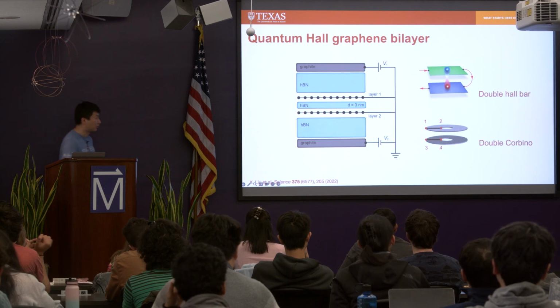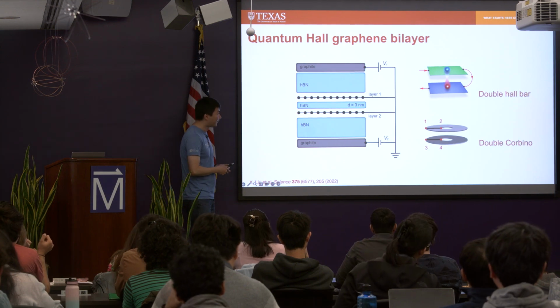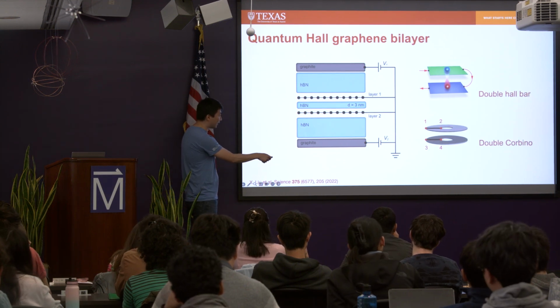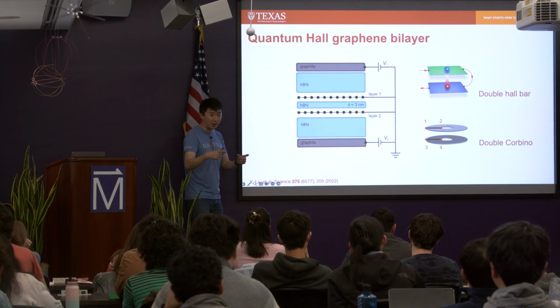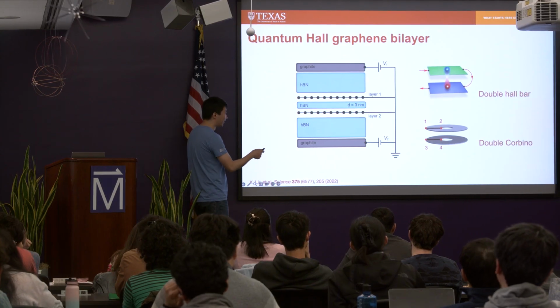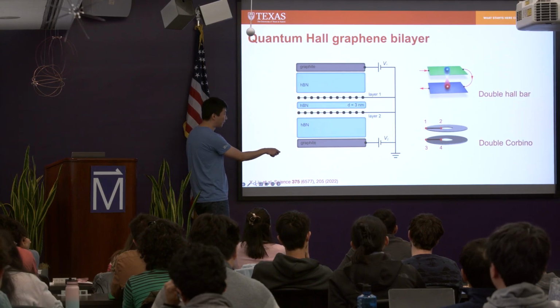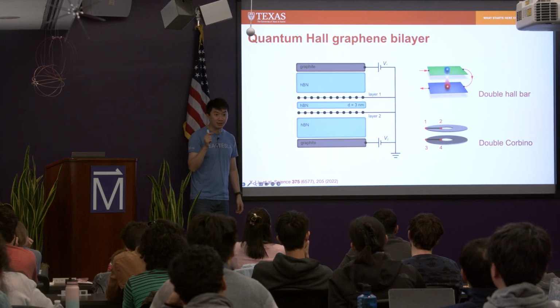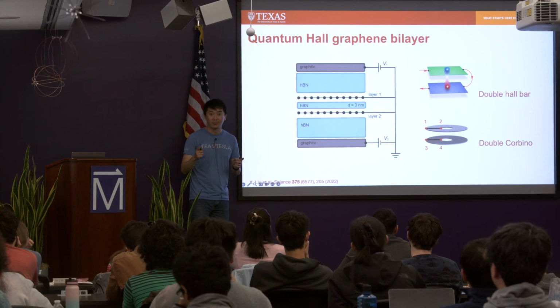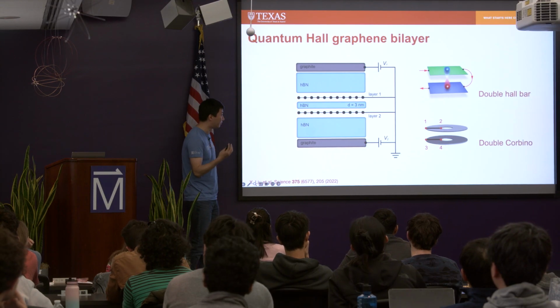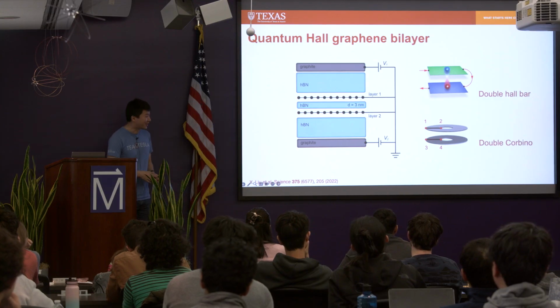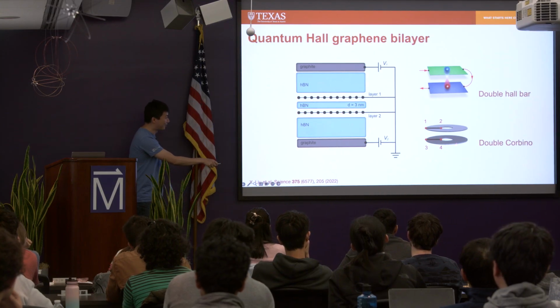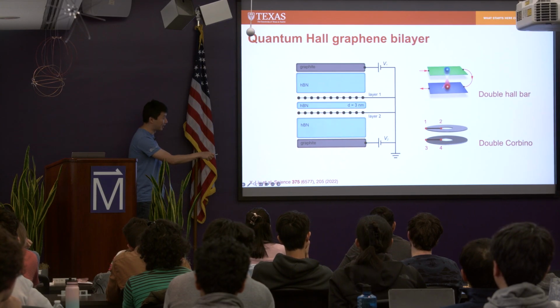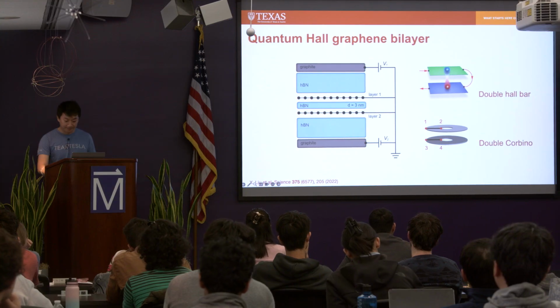Another option is what we call double Corbino, where we pattern each layer into this donut shape, annulus shape, where the advantage here is that when you flow current from the outer edge to the inner edge, there's no edge transport, right? So you directly probe bulk conductance. It turned out that this one is much more advantageous, but I'm going to talk about both configurations.